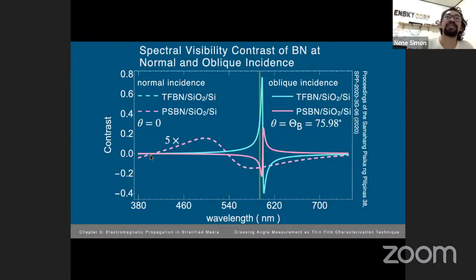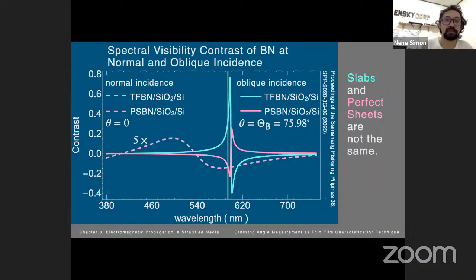So as you can see here, we have the normal reflectivity and the normal contrast measurements. It's very small, and the two models give almost overlapping curves. However, at oblique incidence, the curves are giving different contrast values and signs. And from here, we can say that for oblique incidence, the slab model and the perfect sheet model are not the same.